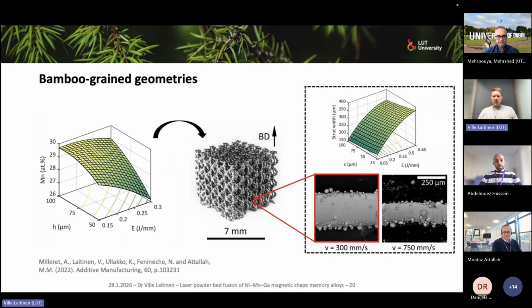Another way we can go at it is something we have worked on quite extensively with Moataz's team. We have what we call the bamboo grain geometry. We don't go directly into foam making, because the foam has a huge fraction of porosity inside it, and the force output of the material will significantly reduce because of this. But in additive manufacturing, we can tailor the porosity very precisely. So in this case, we make lattice structures, and we tailor the parameters in a way that we can achieve a very specific strut width. Then in the post-processing treatment, we can do some tricks where we make this structure locally bamboo grained.